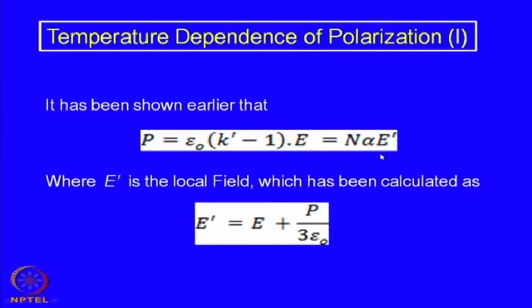Because other dipoles have a certain influence on their neighboring dipoles, the effective electric field is different from what we apply from outside. One can calculate that there is a relationship between the applied electric field from outside and the polarization of that particular volume of material.